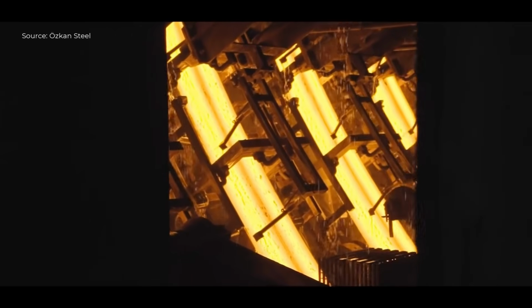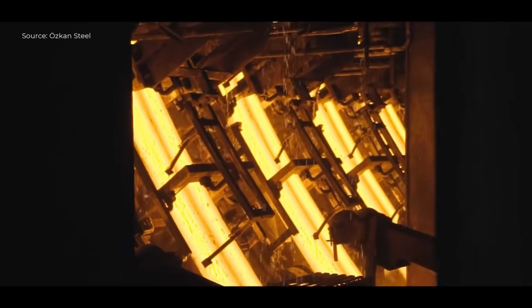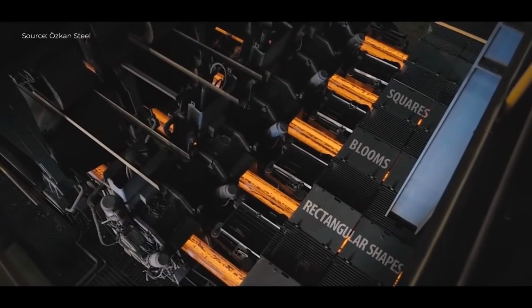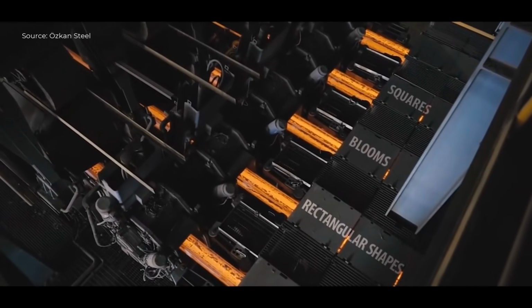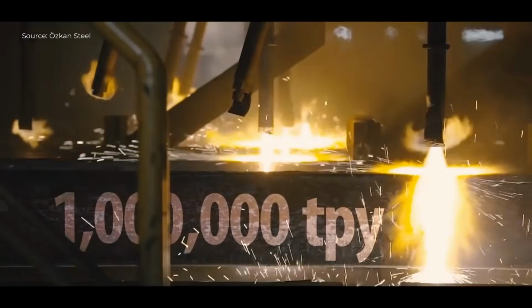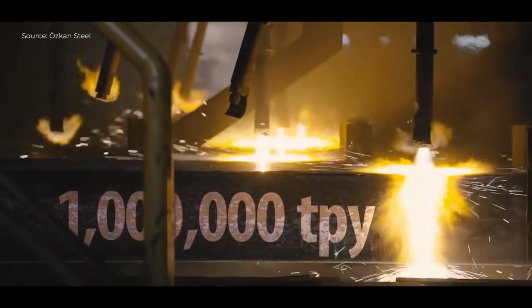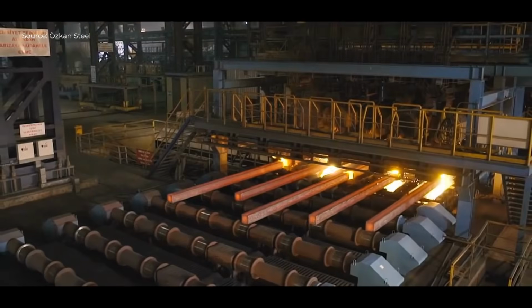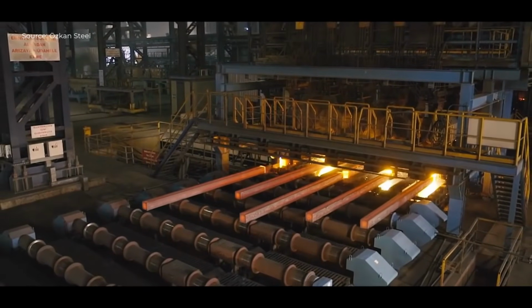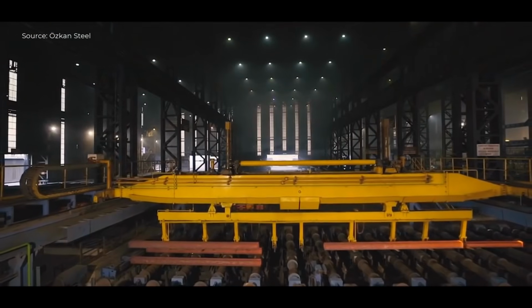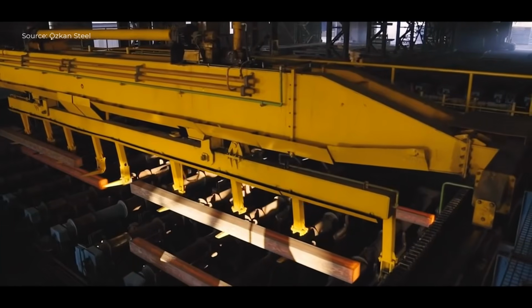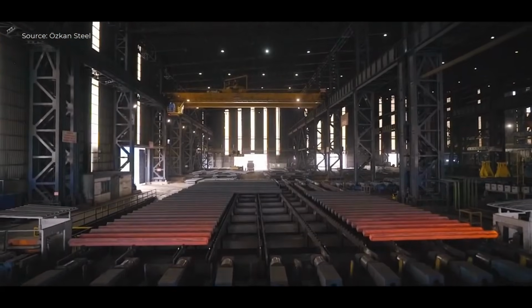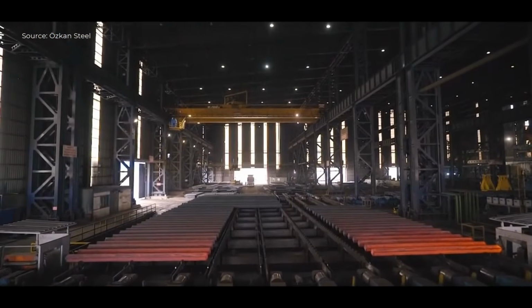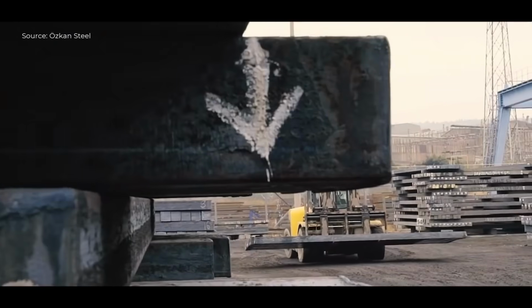When the melting process is complete and the composition is verified, the liquid steel is tapped from the furnace into a ladle. The ladle transports the molten steel to the casting section. From there, the steel is transferred into the tundish of the continuous casting machine. The plant operates a 5-strand continuous casting machine, CCM, enabling simultaneous production on 5 casting lines.